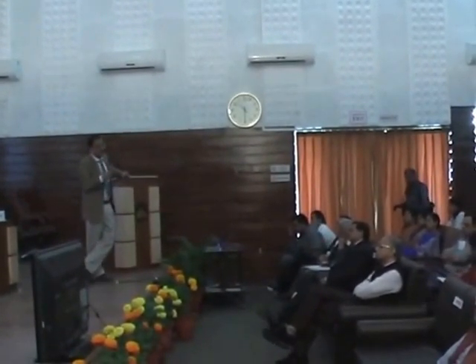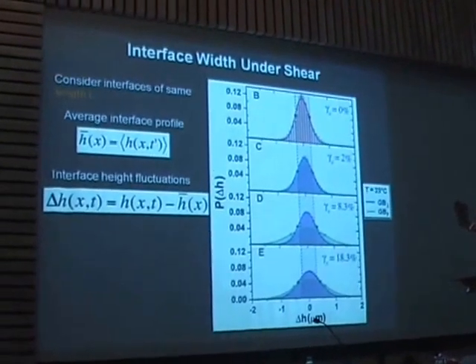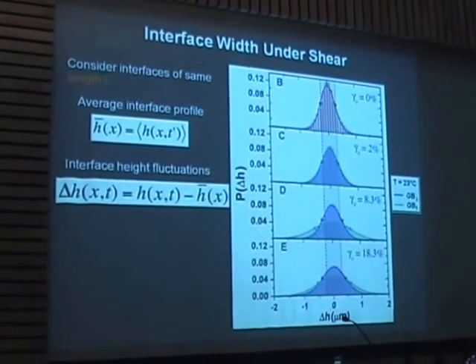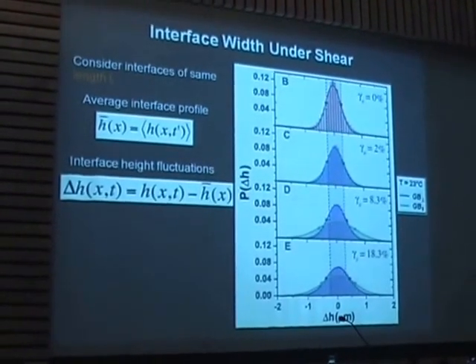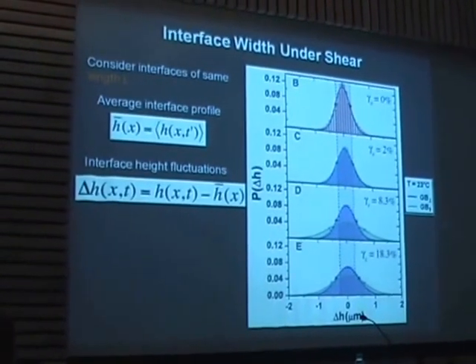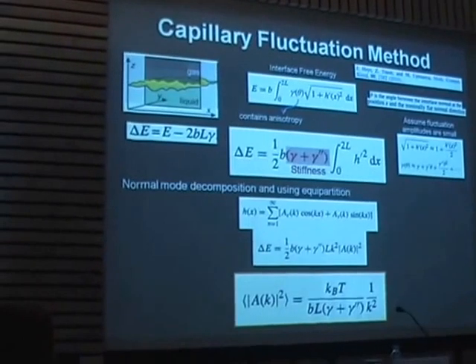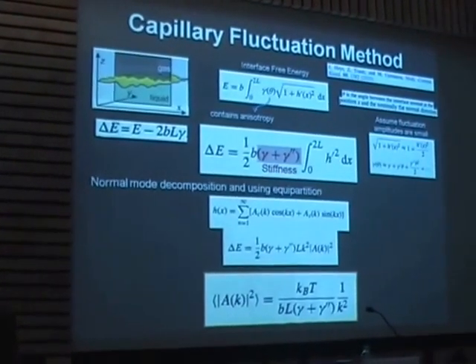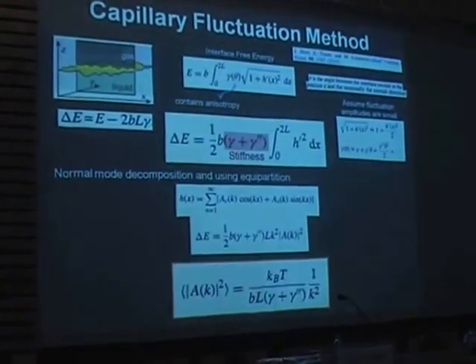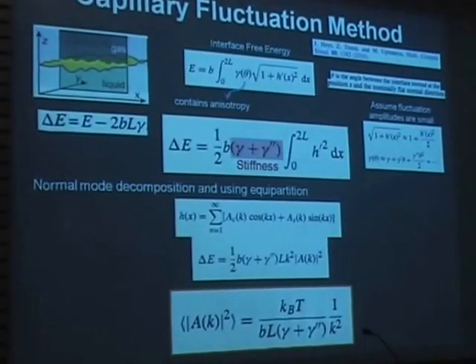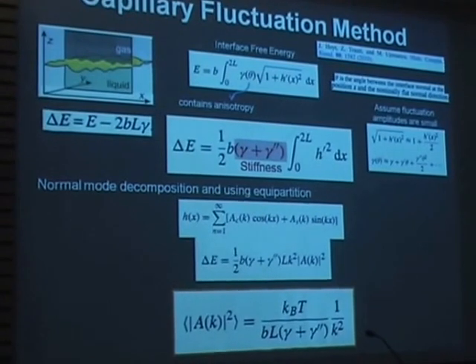When the grain boundary is perpendicular to the shear, it becomes very rough and the grain grows. If it is parallel, not much happens. Now this kinetic roughening, which is anisotropic, is of interest because the grains will grow only along the shear direction. This is something we quantify, because we plot the interface fluctuation as a function of time. One interface is very broad and fluctuating, the other interface is not fluctuating too much. To get across how we do this, for the few people who might be interested, we look at this grain boundary as if it is a surface. How does it fluctuate? You know that a water surface on a trough fluctuates, so we analyze it exactly the same way.